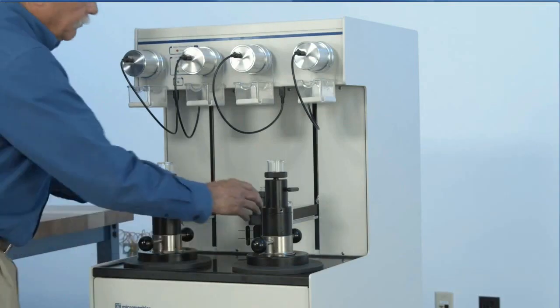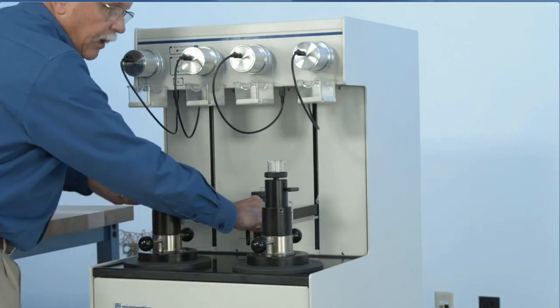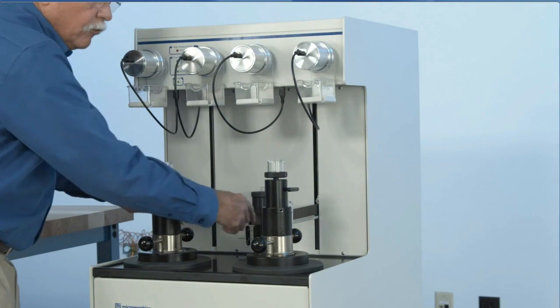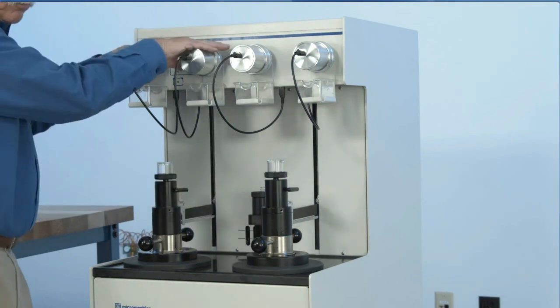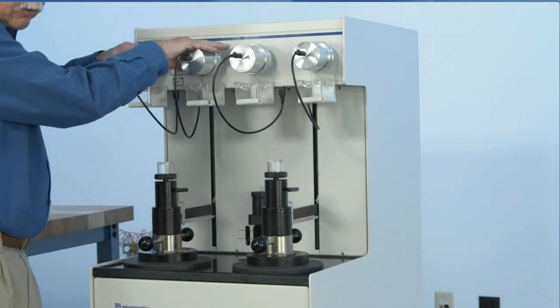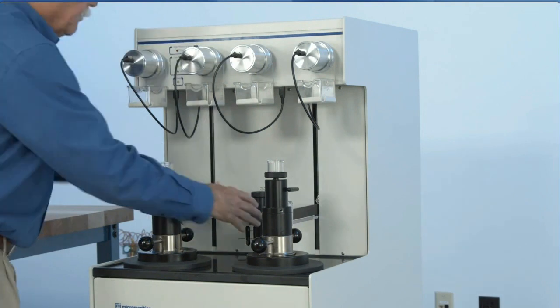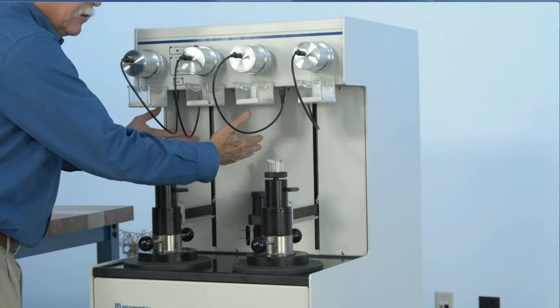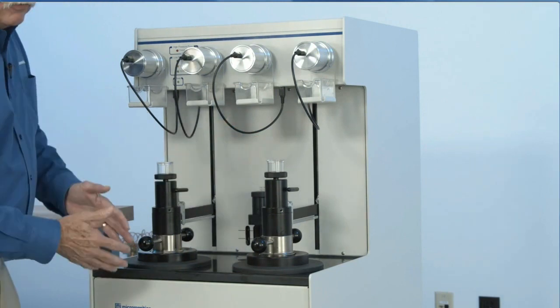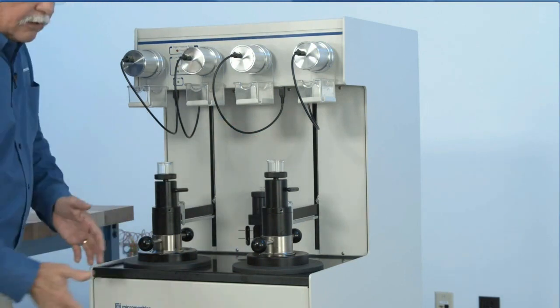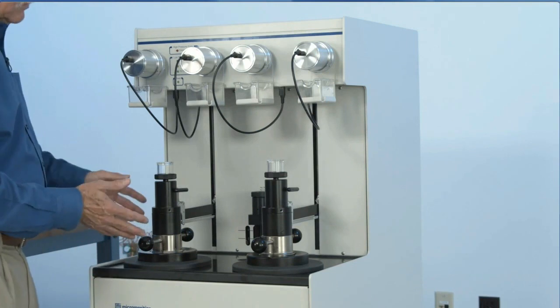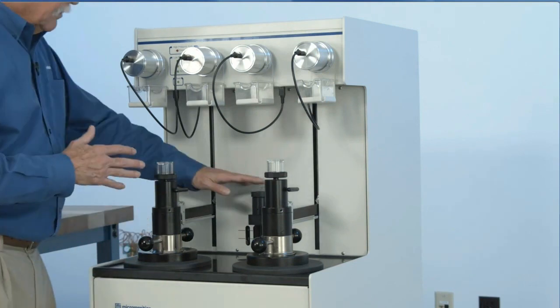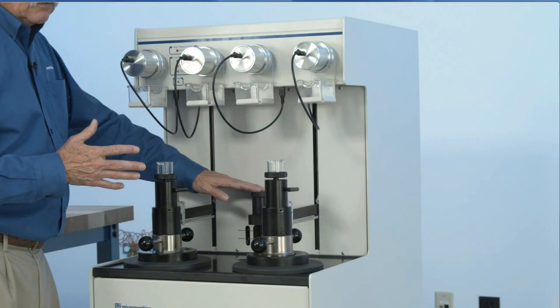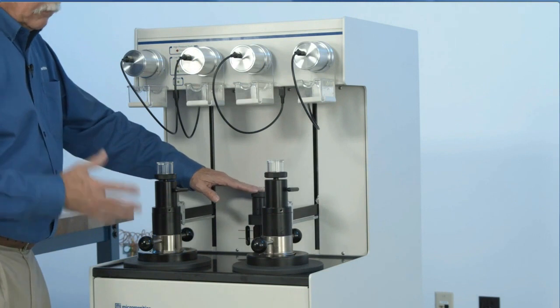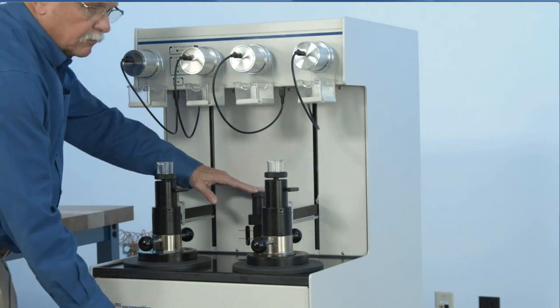We keep the mercury reservoir, which is our supply of mercury during the analysis, and we move bulk mercury up into the low pressure ports, always under vacuum. We never pressurize the mercury as we're moving it. We move it only under vacuum. But we keep the mercury in the top part of the instrument away from those heat-producing components. There are fans inside to help pull the heat out of the instrument. So again, we want to keep the temperatures around the mercury constant. We want to keep them about room temperature, so all the heat-producing devices are in the bottom.